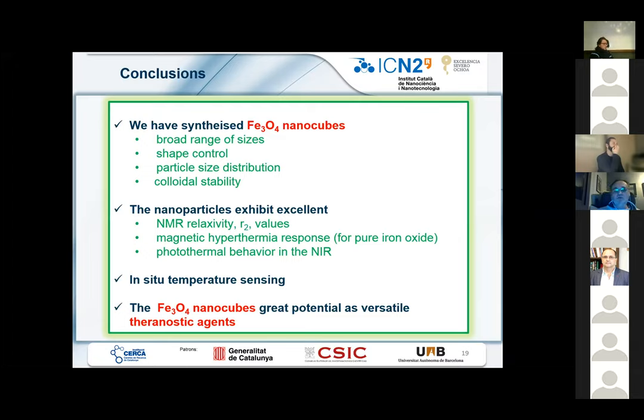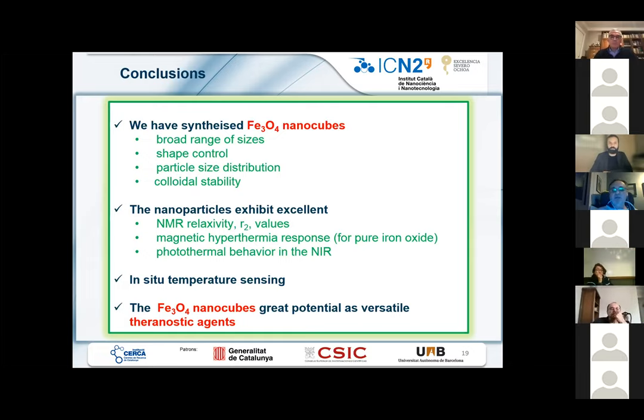So in conclusion, I hope I have convinced you that we can synthesize Fe3O4 nanocubes in a broad range of sizes with good shape control, a good particle size distribution, and good colloidal stability. The nanoparticles exhibit excellent MRI relaxivity values, good magnetic hyperthermia response, especially for pure iron oxide particles, and good photothermal behavior in the near infrared. And we can use these nanoparticles also for in situ temperature sensing. So this means that the Fe3O4 nanocubes have great potential as versatile theranostic agents.